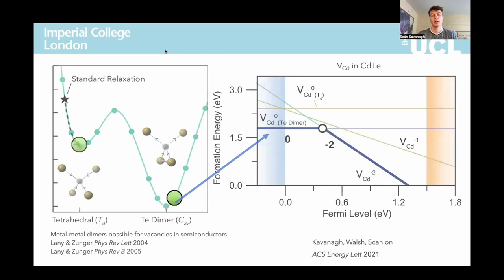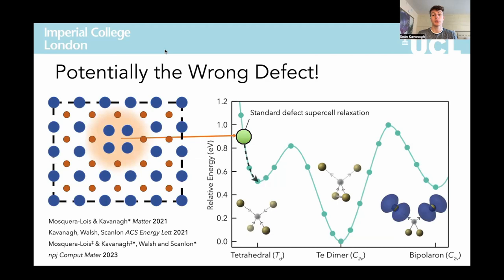The core problem is that when we generate our initial defect structure in this way, there's actually no guarantee that this will give us the true ground-state defect structure. This is the workflow — gradient optimisation — that is followed by essentially all ab initio defect studies. The ideal undistorted defect structure could actually lie much closer to a local minimum on the potential energy surface, which would then give us a higher-energy metastable structure that does not reflect the true defect behaviour.